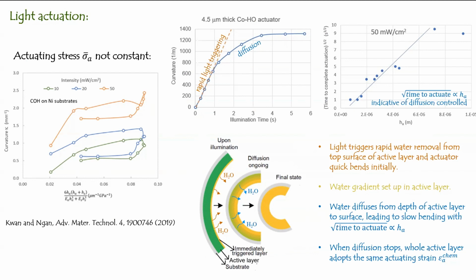And then if you plot the square root of the time to actuation, so that kind of time, versus the thickness of the active layer, you see more or less a linear plot. So that tells you that diffusion is also involved. So light actuation is a lot more complicated because light can only penetrate a very shallow layer initially.